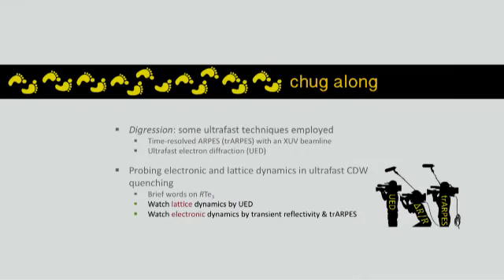Okay, yeah, so now let's go into the experimental results section, where what we're really doing is we use three different ultrafast probes: specifically ultrafast electron diffraction, transient reflectivity, where we measure basically how the reflectivity changes as a function of time after the pump pulse arrival, and then, as I explained, time-resolved ARPES. We first look at how the lattice dynamics evolve, and then look at how the electronic dynamics evolve.